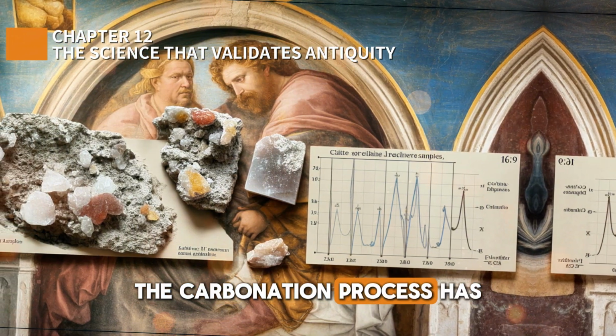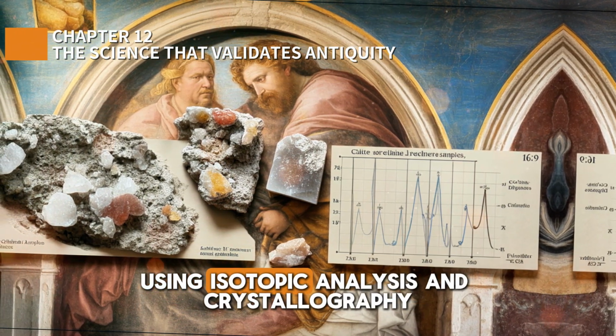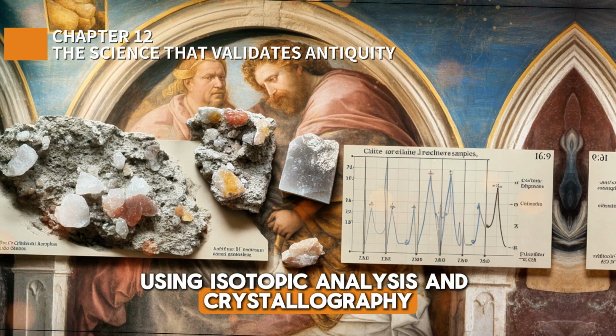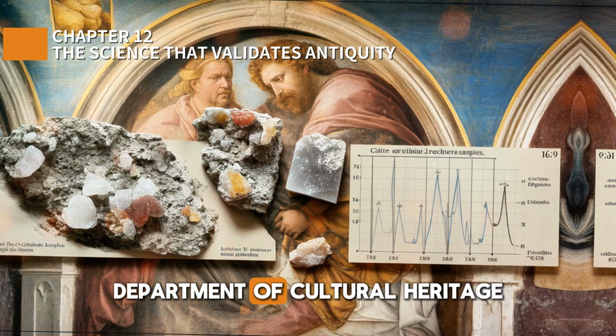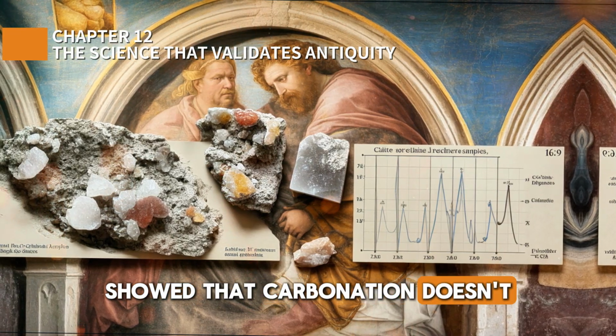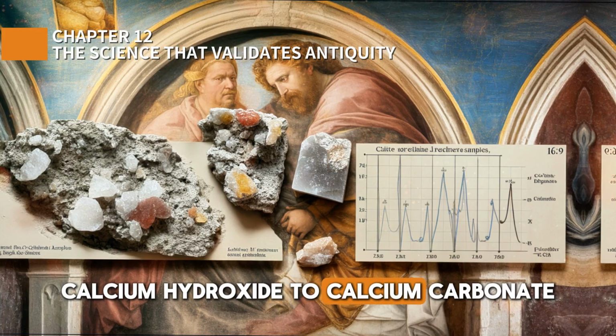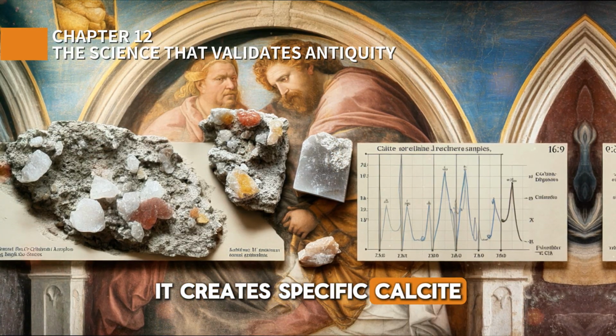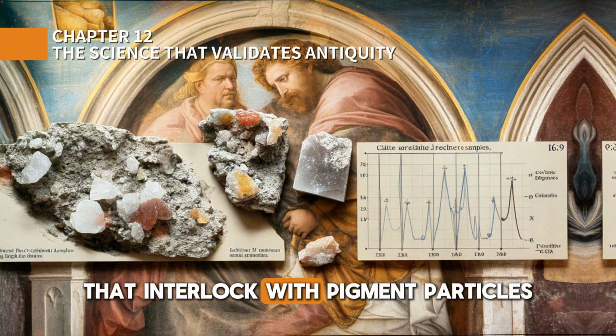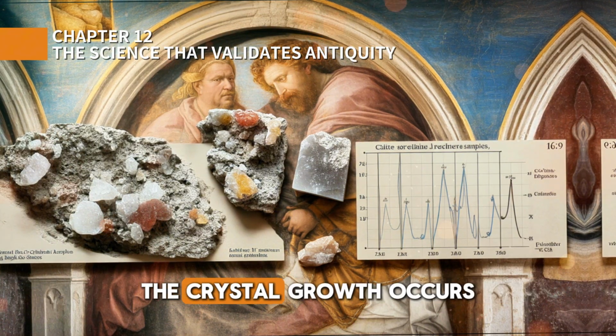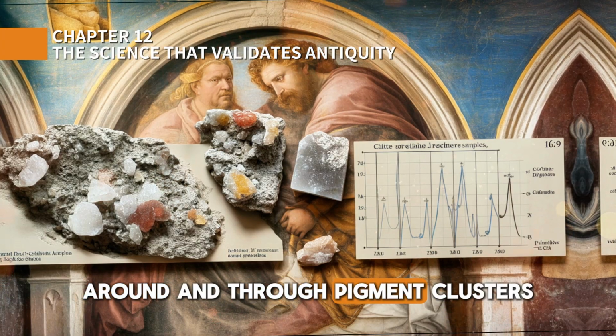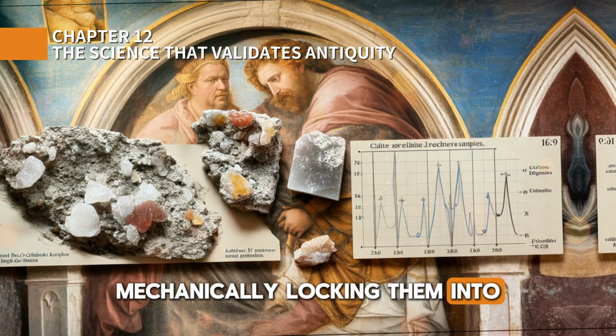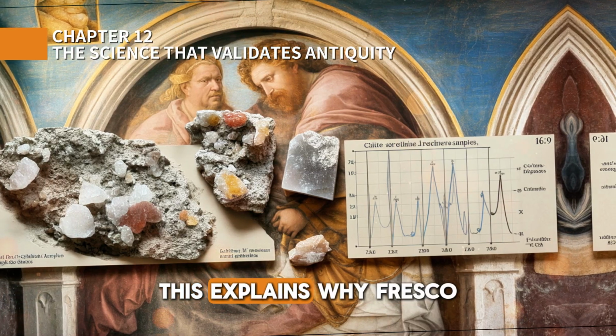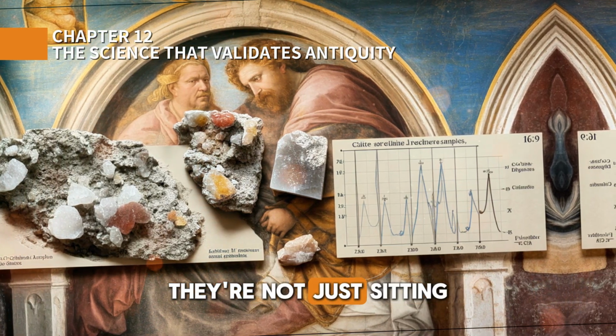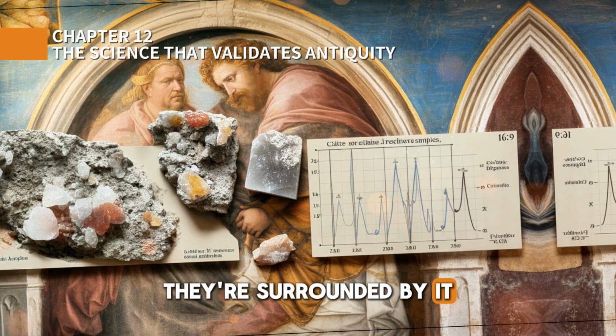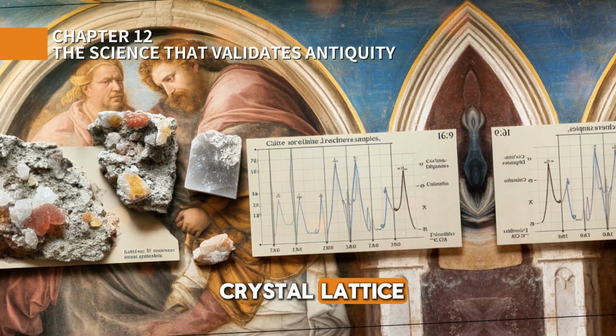The carbonation process has been studied in detail using isotopic analysis and crystallography. Research at the University of Bologna's Department of Cultural Heritage showed that carbonation doesn't just convert calcium hydroxide to calcium carbonate. It creates specific calcite crystal structures that interlock with pigment particles. The crystal growth occurs around and through pigment clusters, mechanically locking them into the plaster matrix. This explains why fresco pigments are so permanent. They're not just sitting in calcite, they're surrounded by it, trapped in a three-dimensional crystal lattice.